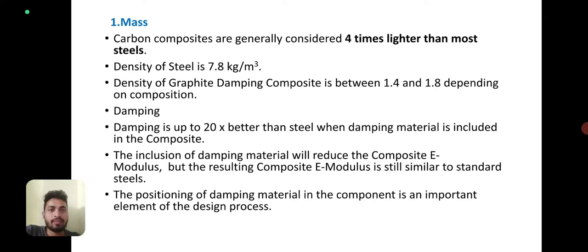The first one is mass. Carbon composites are generally considered 4 times lighter than most steels. Density of steel is 7.8 grams per cubic centimeter. Density of graphite damping composite is between 1.4 and 1.8 depending on composition. It has good damping. Damping is up to 20x better than steel when damping material is included in the composite. The inclusion of damping material will reduce the composite E modulus. The resulting composite E modulus is still similar to standard steels. The positioning of damping material in the component is an important element of the design process.